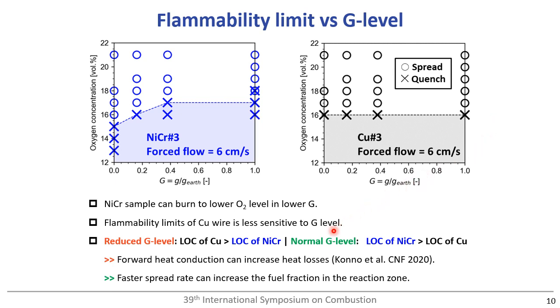And in our previous work, we clarified why a high conductivity wire can increase the LOC of insulation material. This is caused by the forward heat conduction through the wire core. We clarified that forward heat conduction can preheat the insulation, but it can increase the heat loss from the system during the flame spread event. As a result, a highly conductive wire can increase the limiting oxygen concentration. On the other hand, the cause of a smaller LOC in the high convective condition remained unclear. One of the possible explanations is the difference in flame spread rate. A highly conductive wire can increase the flame spread rate, and this can increase the fuel concentration in the reaction zone. So the flame along the highly conductive wire could be more stable and harder to blow out.